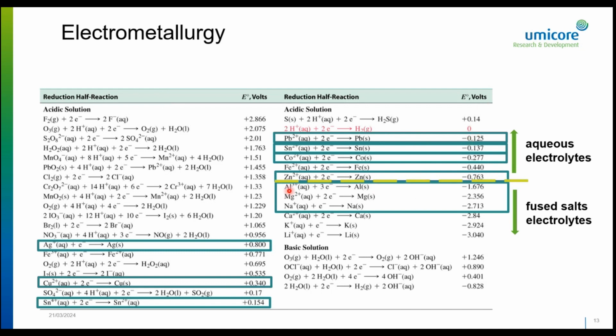But for instance, if you're looking at these type of metals like aluminum, magnesium, sodium, you cannot produce these metals in water media, because then you will just convert your water instead of reducing your metal. So then you need to look to other media such as fused salts. But all the other metals indicated here you can process in aqueous media. And so this is mainly about the reduction of metals. The counter reaction at the anode is usually, as I said, oxidation of water to oxygen. So that's what usually happens at the anodes.